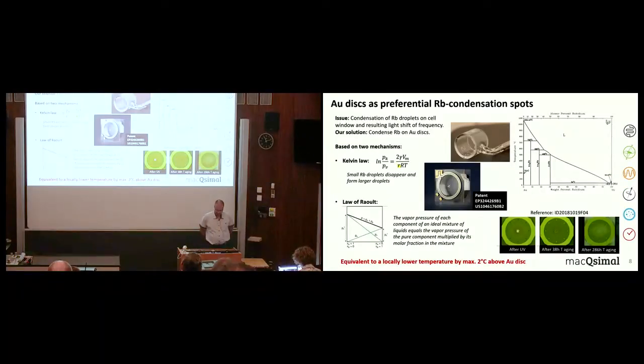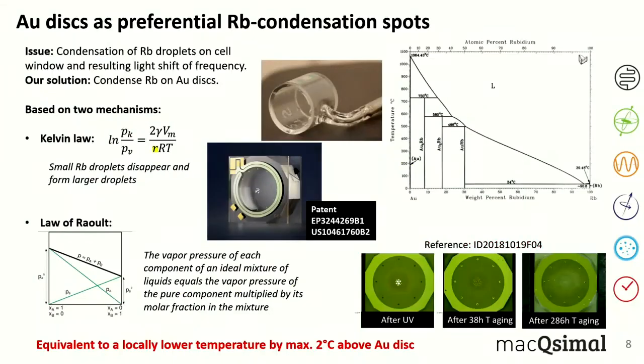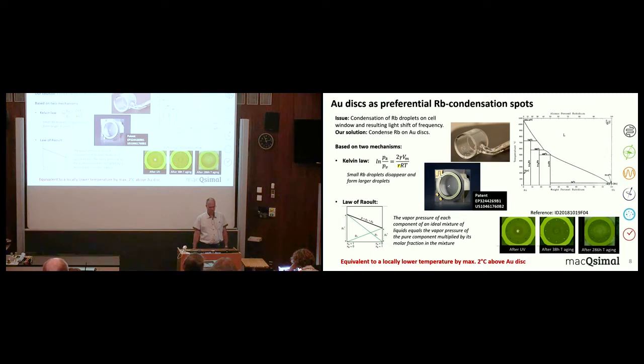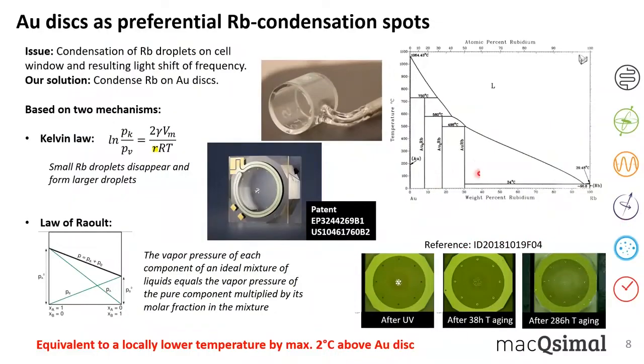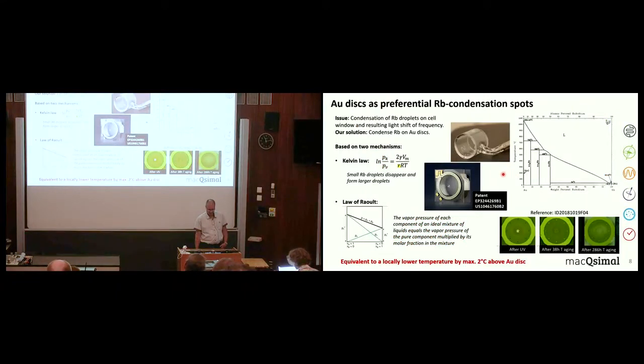In the first activities to produce vapor cells many years ago, among other tests, we tried to bond the glass wafer onto the silicon cavity wafer by gold-gold thermocompression bonding. And when we analyzed the cells sometime later, we discovered there was no rubidium inside anymore. And when we looked more in detail, we discovered that all the rubidium was sitting on the gold seal. So indeed, there exists a binary phase diagram of gold and rubidium. As you can see here, there are several stable phases, and they have a very low eutectic temperature of, what is it, 34 degrees Celsius.